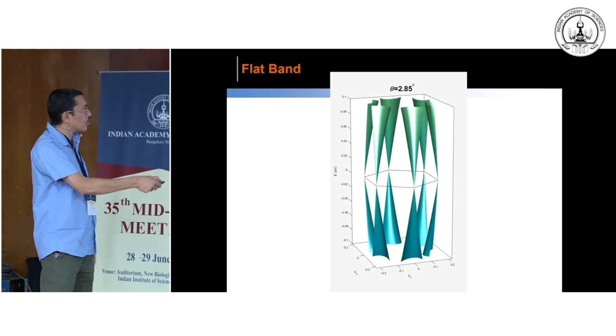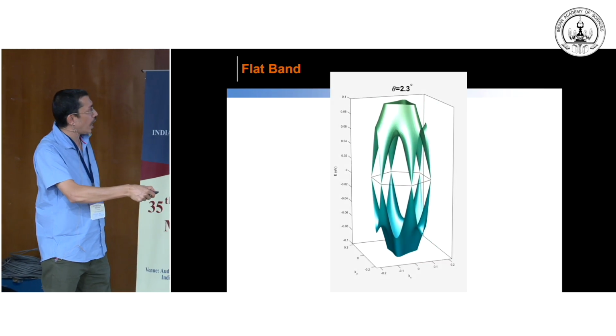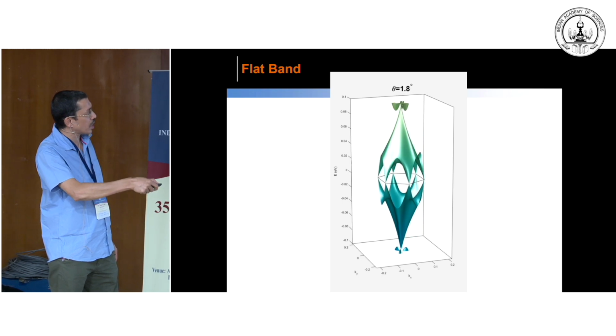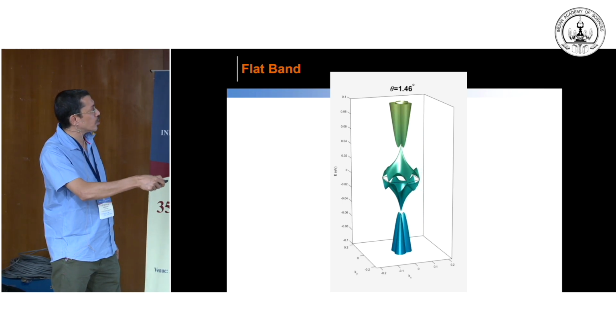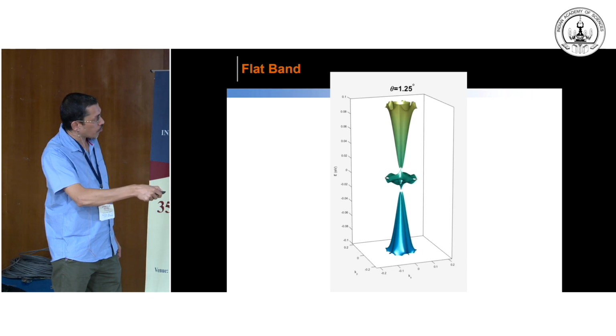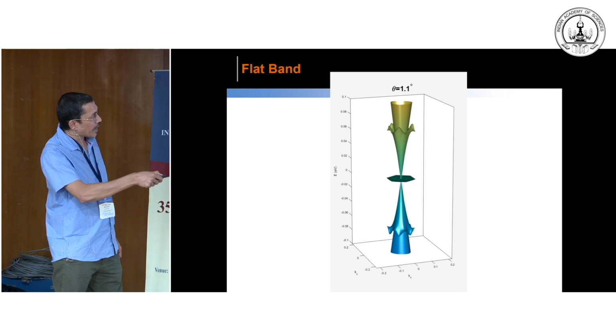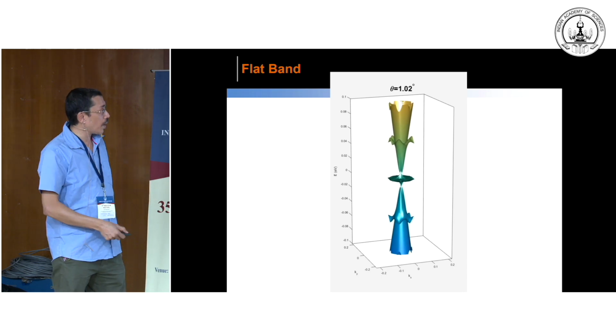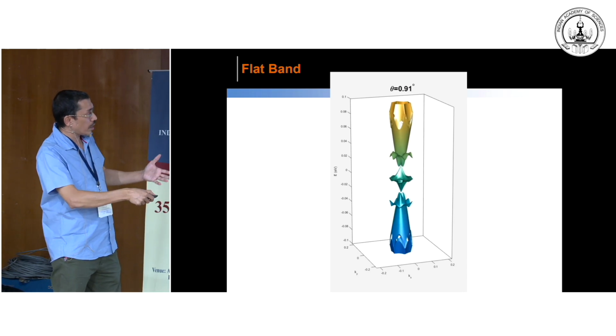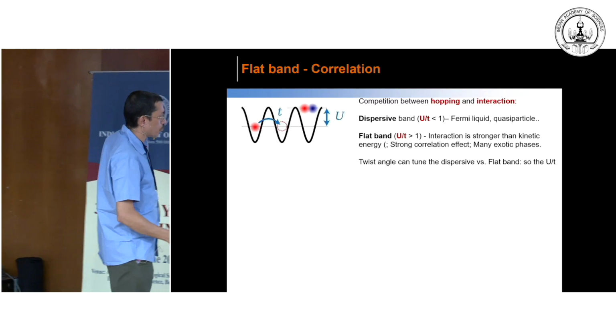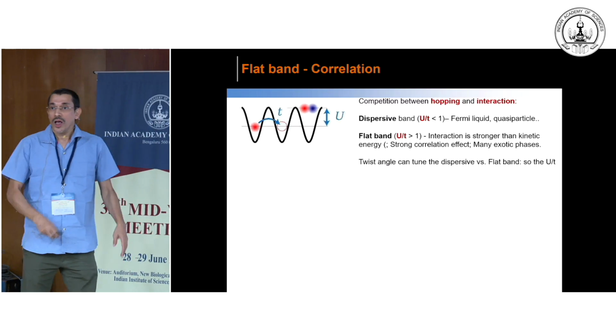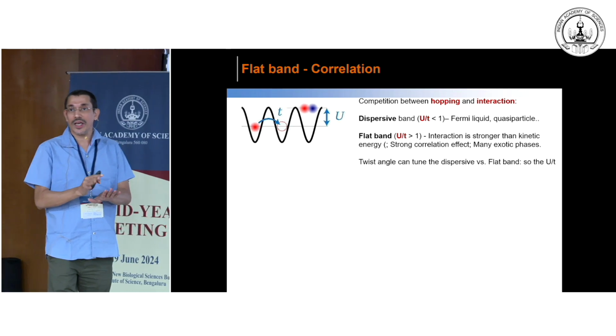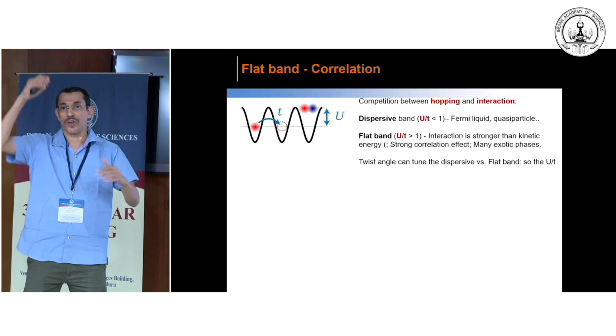So this is a cartoon picture I have taken from Pablo's slide, and this tells you how the band structure changes with the twist angle. As you reduce the twist angle, the width of your low energy band becomes flat, and in fact at the magic angle it really becomes flat. Even if you reduce further, the band becomes a little dispersive again, and so on. So okay, in twisted bilayer there is a flat band which is isolated from the dispersive band.